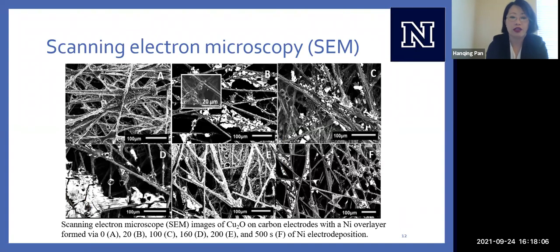So these are always fun images to look at. We can look at our catalyst under a scanning electron microscope. And when we zoom in, we see this spiderweb-like structure. This is very similar to what we see with a piece of paper, with all the cellulose of the paper. And the brighter spots on top are the copper oxide and nickel. The copper oxide and nickel is preferentially depositing along the spindles and fibers of our carbon paper.